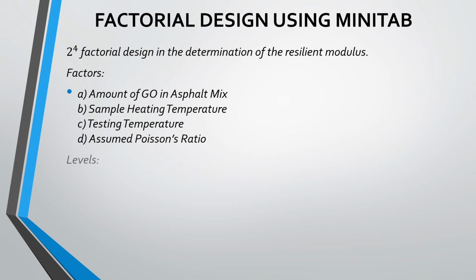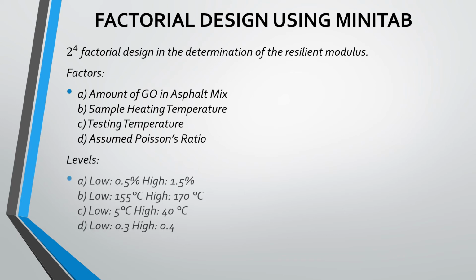For the first factor, the low will be at 0.5% and the high will be at 1.5%. Second, the low will be at 155 degrees Celsius and the high will be at 170 degrees Celsius. For the third factor, the low will be at 5 degrees Celsius and the high will be at 40 degrees Celsius. And lastly, for the fourth factor, the low will be at 0.3 and the high will be at 0.4. The response of the factorial design will be the resilient modulus of the GO-modified asphalt.